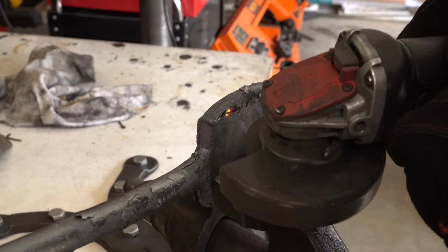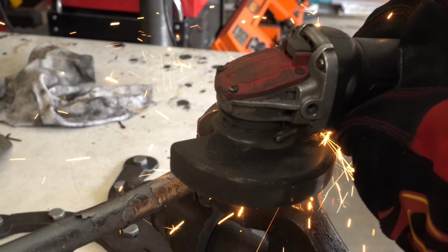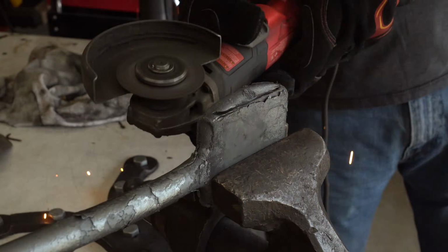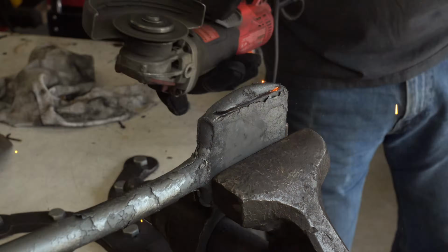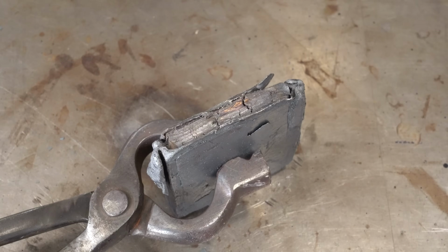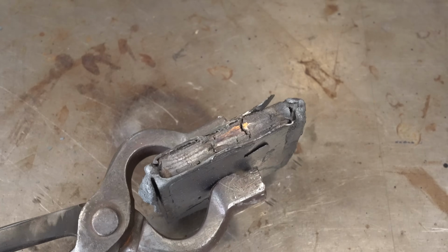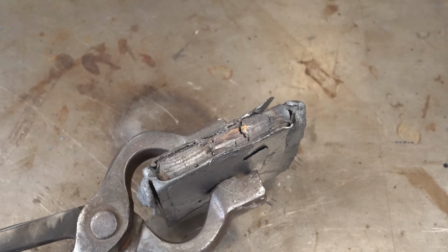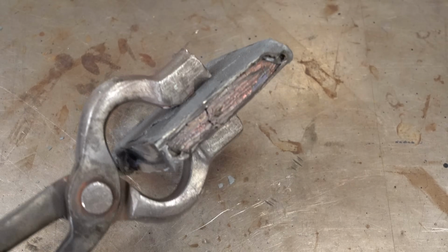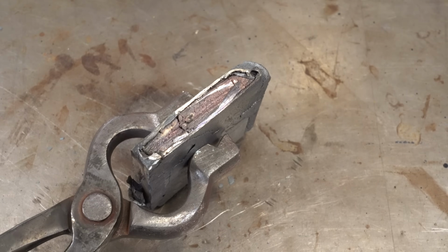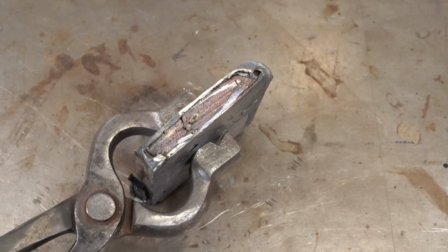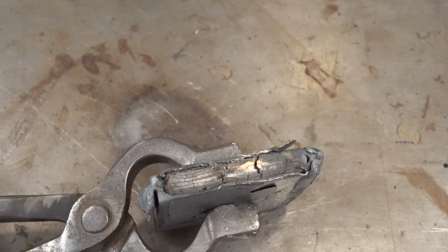Now it's time to remove the canister and see how we did on the second weld. So here it is after the forge weld. Looks pretty good, actually better than even the first weld. You know, a couple cracks on the sides, which I expected, and I'll be grinding out. But yeah, it looks pretty good.